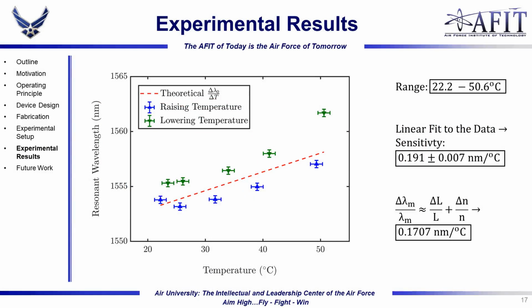The central wavelength of the resonant feature is extracted from this fitting and plotted in this figure at each temperature used during the experiment. The vertical and horizontal error bars represent the accuracy of the test setup and fitting and the thermocouple respectively. The dashed line plots the theoretical change in wavelength for the theoretical changes in cavity length due to thermal expansion and refractive index with air temperature. The intercept is chosen arbitrarily to place the line on top of our data, and the coefficient of thermal expansion used for this calculation was derived experimentally in our group's previous work. The shift in resonance we observe follows a linear trend and matches the slope of the predicted shift nicely.